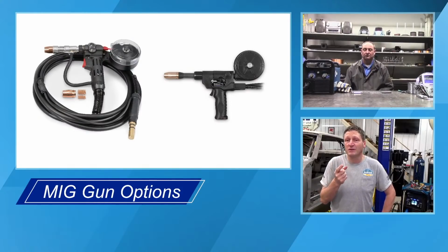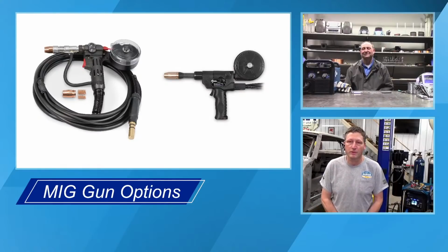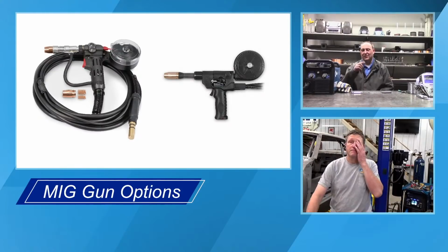And don't be surprised if you get a bottle of 100% argon and sometimes you'll get a contaminated bottle. Those bottles probably weren't 100% argon their whole entire life. And if they didn't pull a good enough purge on the bottles before they filled them, there could be some residual CO2 in some of those bottles. So that will cause not only some soot, but the puddle will look scummy, like you're not just getting that shiny puddle anymore. It feels like the wire is just kind of digging into the base metal, and that's an indication of some contamination, normally through gas.